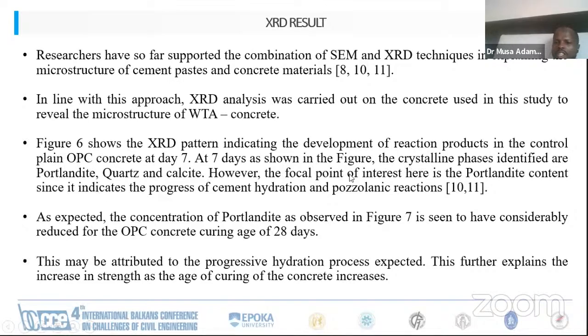However, the focal point of interest here is the portlandite content, since it indicates the progress of cement hydration and pozzolanic reactions. As expected, the concentration of portlandite, as observed in figure 7, is seen to have considerably reduced for the OPC concrete curing at 28 days. This may be attributed to the progressive hydration process expected. This further explains the increased strength with the age of curing.